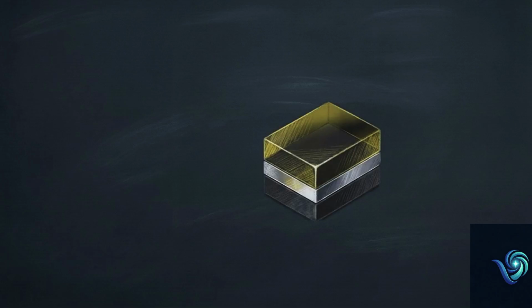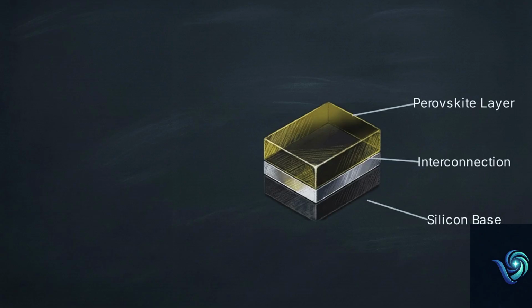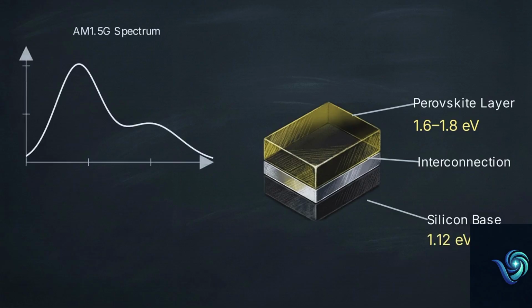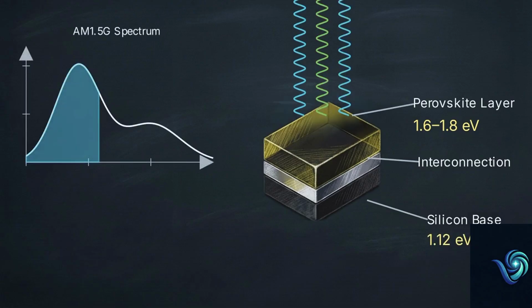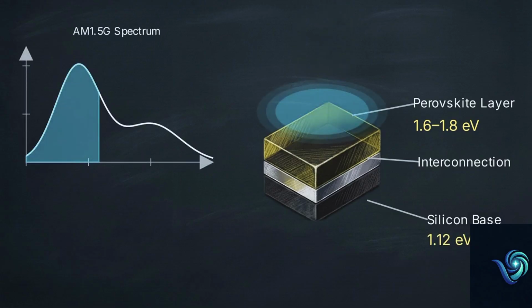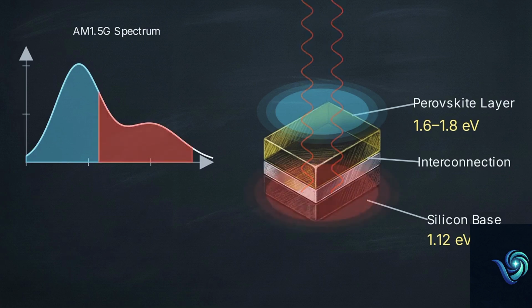This is an isometric cross-section of a two-terminal perovskite-silicon tandem cell. A thin perovskite top layer is separated from a thicker silicon bottom layer by an interconnection layer. The perovskite top layer is tuned to a wide bandgap between 1.6 and 1.8 electron volts, positioning it directly above the 1.12 electron volt silicon subcell. High-frequency blue and green light is absorbed entirely by the perovskite. The remaining low-energy red and infrared photons pass cleanly through the top layer, stopping inside the silicon layer below.